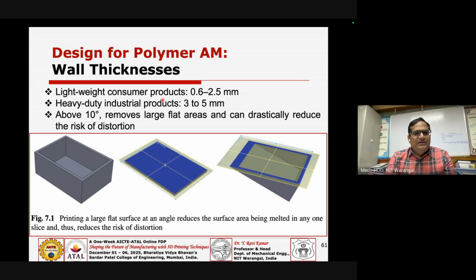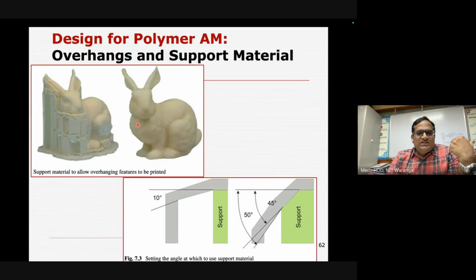And wall thickness could be 0.6 to 2.5 mm for lightweight consumer products, and for heavy duty it may be 3 to 5 mm. Also, better not to lay parts in this orientation. Why? Because you have huge residual stresses building up in a single layer. But instead of making this orientation, you make it at some 10 degrees, where the residual stresses are accumulated not in a single layer but maybe 10 layers, 20 layers, again depending on the layer thickness that you're using. So you can consider all these design constraints, rather than guidelines, to fix your orientation, wall thickness or whatever. And then for support structures, your overhang angle is going to play a major role.